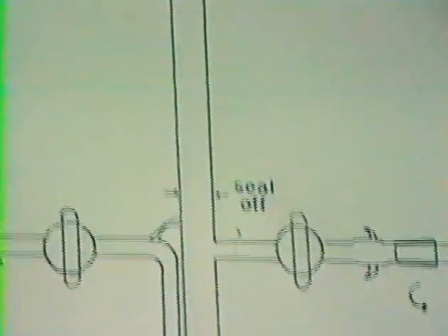And then as a third technique, we use XAFS. We did the XAFS measurement at the Photon Factory in Japan, and we used this Pyrex reactor. We placed the disk sample here, and then we heat it by flowing hydrogen, and we turn this upside down, like this. While we flow hydrogen through here, we made a seal with a glass torch, the flame. So we obtained just this, and we brought this to Japan to measure the XAFS very quickly.